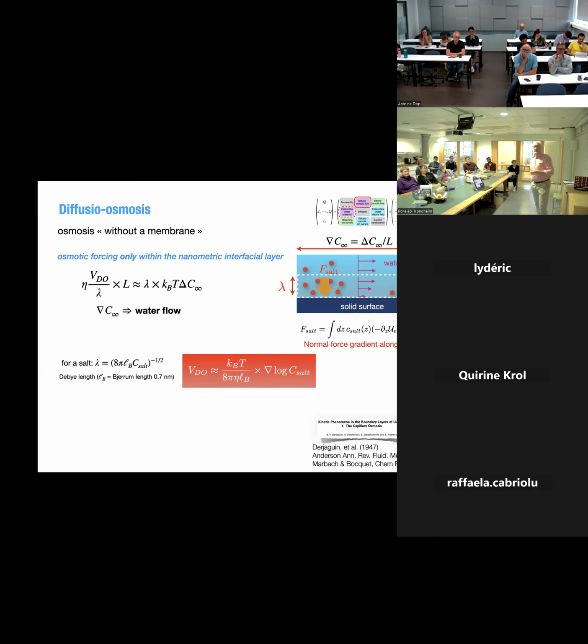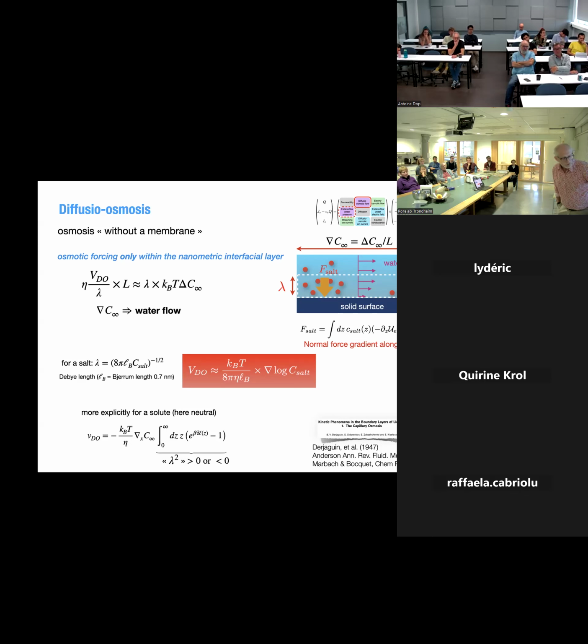You can put this in equation by making a force balance here. You have the viscous stress along this distance here. That's hydrodynamic stress. And then the pressure drop comes from the two ends. So it's kBT delta C, the difference of concentration, acting only over the Debye length, because above, there is nothing like osmotic pressure. There is no separation. So then you have indeed velocity scales like lambda squared times the gradient. For a salt, the length is also proportional to the inverse square root of concentration. So then you can rewrite this as the gradient of the log of salt concentration for a salt. Not in general, but if you take a neutral solute, this lambda squared is proportional to the excess of solute at the surface.